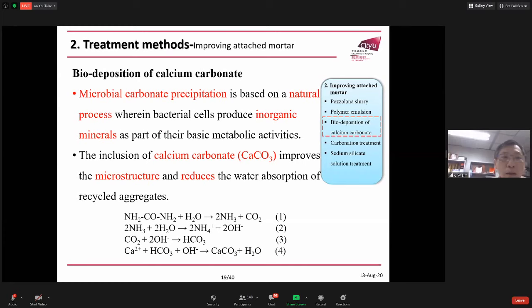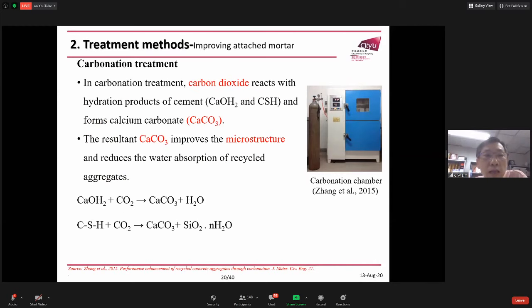The other treatment method is by biodeposition of calcium carbonate. Microbial carbonate precipitation is based on a natural process wherein bacterial cells produce inorganic materials as part of their basic metabolic activities. The inclusion of calcium carbonate improves the microstructure and reduces water consumption. Some chemical reaction properties are presented here. One other method is carbonation treatment. In this case, carbon dioxide reacts with hydration products of cement and forms calcium carbonate. The resultant calcium carbonate improves the microstructure and reduces the water absorption of recycled aggregates.